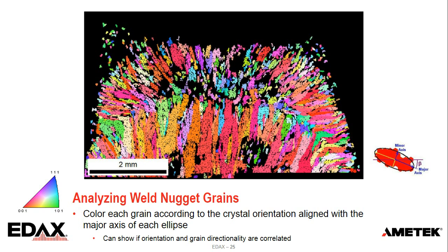And we can see there are a number of grains aligned top to bottom in that A1 axis, which explains that orientation distribution in the pole figures.